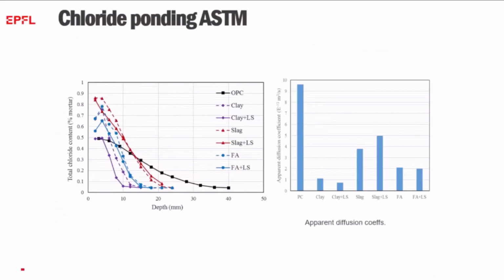Chloride resistance, also outstanding. And these are the blends I showed you earlier, the binary and the ternary blends based on clay or slag or fly ash. And here is the reference Portland cement, very deep chloride penetration. Here are the slag blends, they're better, the fly ash better again, but the best of all are the calcined clay blends, and the best one is the combination of calcined clay plus limestone. And the effective diffusion coefficients of the calcined clay plus limestone are 10 times lower than the reference.